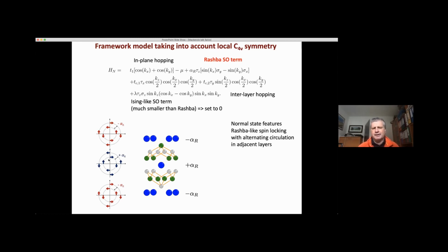Because you're only locally and not globally centrosymmetry breaking, inversion breaking, what you end up having is you have no net Rashba circulation in the material, but you have one direction of Rashba circulation associated with these cerium sites and a second direction of Rashba circulation, a counter direction, associated with these cerium sites. And they're related through the global inversion that exists in the material. So if you now turn on the c-axis hopping, you turn up the coefficients of these c-axis hoppings, what you get is that simple picture is going to mix. You're going to get mixing between the bands that have given this counter circulation, but nothing substantially changes about the argument. So the basic arguments of what you can expect survive this mixing,